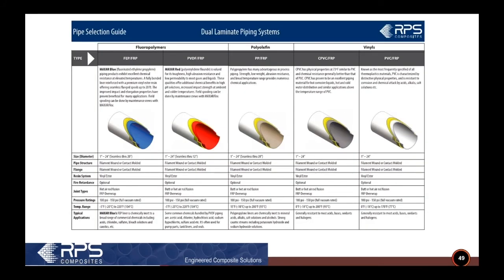Here's a quick overlay of the types of dual laminate pipe you can make. The premiums are going to be the fluoropolymers. They're what we call our HPPE, so our high performance pre-engineered pipe. Those are the ones that are in stock and most commonly used because they cover the widest array of service conditions. Sometimes you can get it in a polypropylene or the CPVCs, PVCs. Those are used in chlorine services. They're a little less expensive than the fluoropolymers. But like I say, overwhelmingly, we probably supply FEP and PVDF for dual laminate systems.